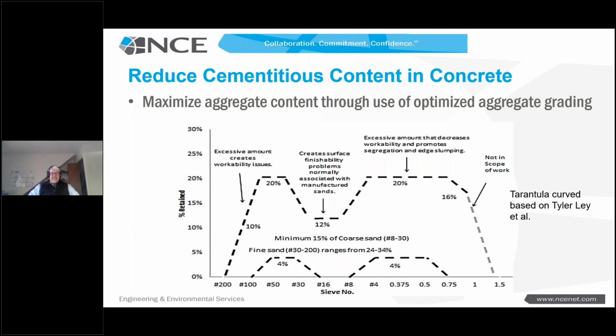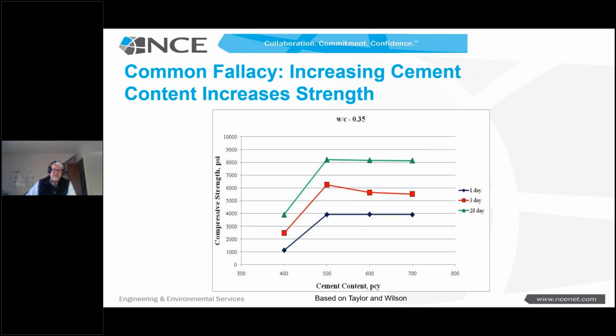With this, you can easily take a mix that might have 564 pounds, or 611 pounds per cubic yard of cementitious materials, and pull out 50, 60, 70, even 100 pounds of cement out of your mix. There's a common fallacy, and I see it time and time again, that more cement in a concrete means more strength. And it's simply not true if a mix is properly proportioned.